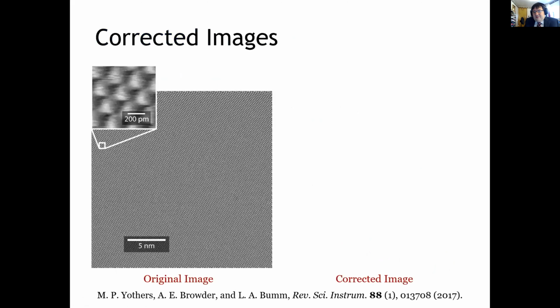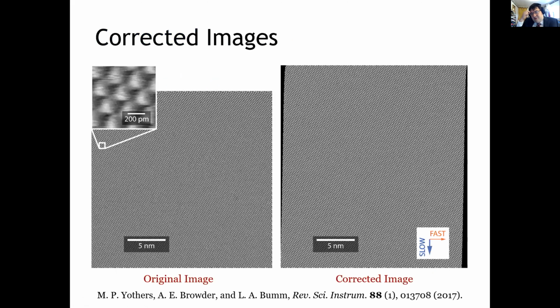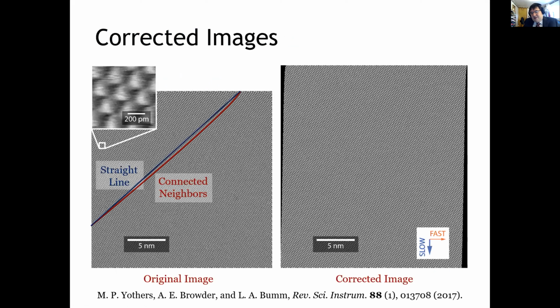So if we take these and apply these to our image, instead of a square image that's distorted, we get this output image that's much less distorted. And so here's a row of connected neighbors, which should obviously be a straight line in a lattice, and here's a straight line. You can see they don't overlap, but on the corrected image, the straight line and the connected neighbors do overlap.